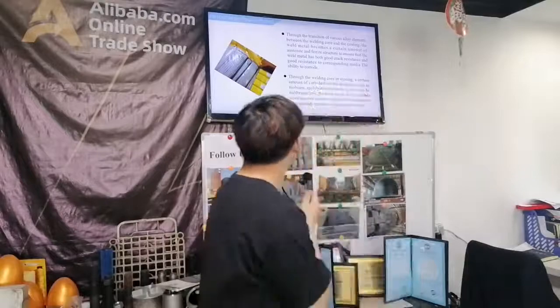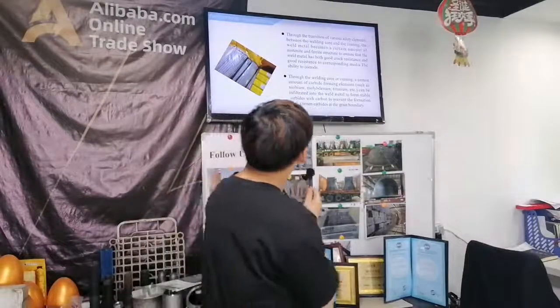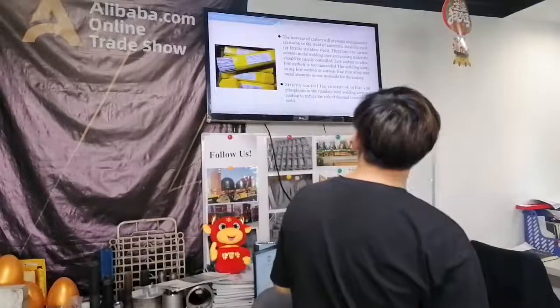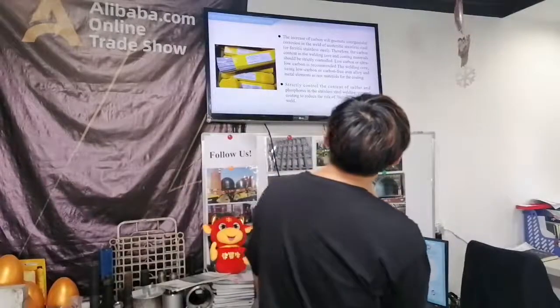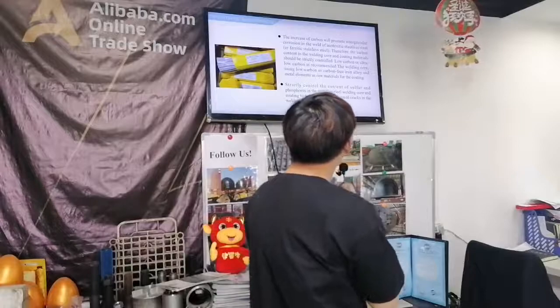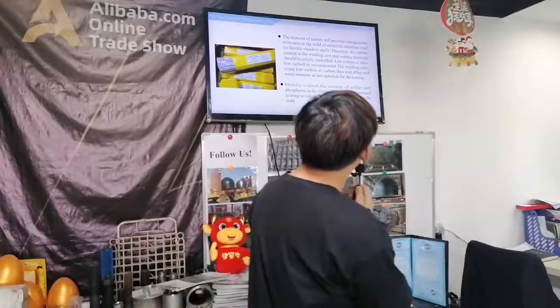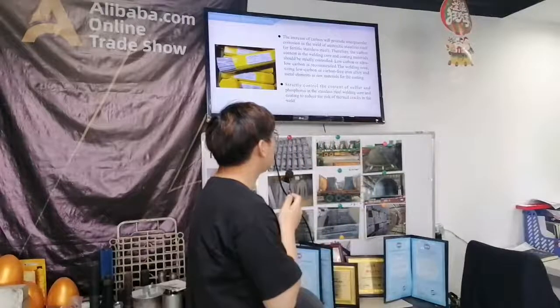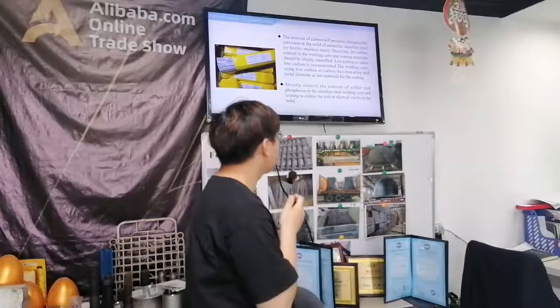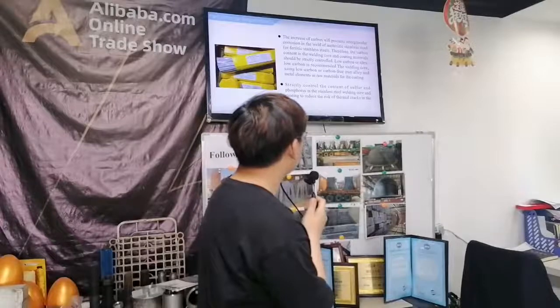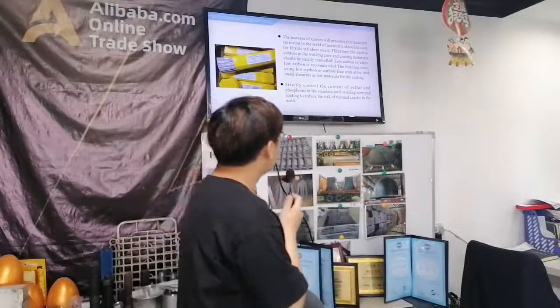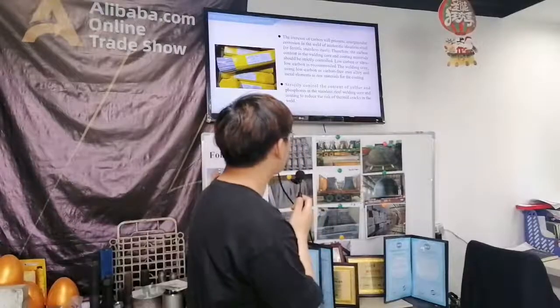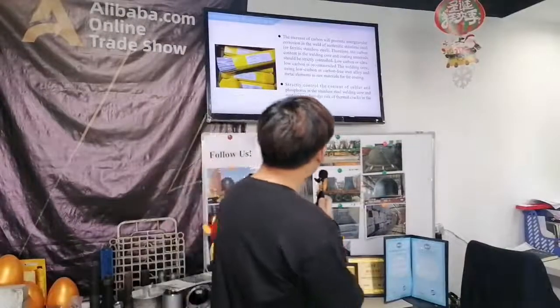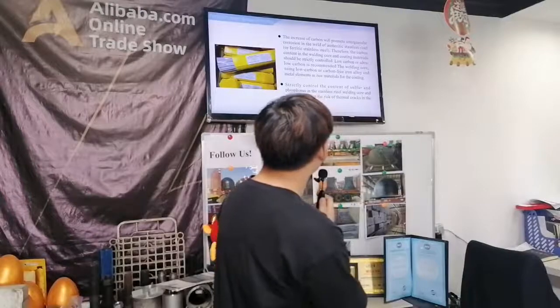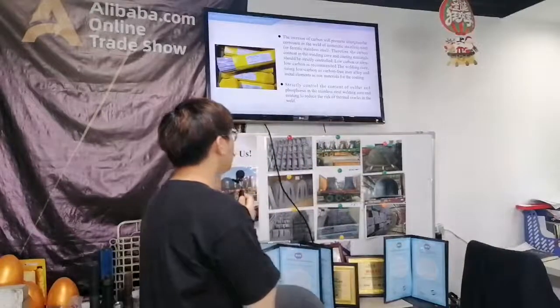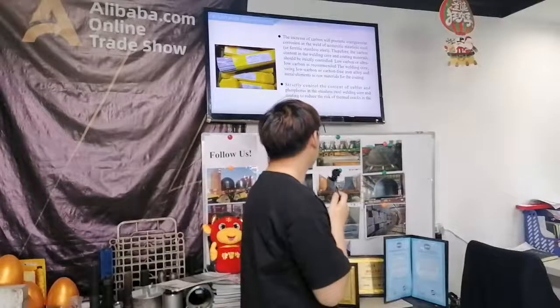And then I will introduce the performance requirements. The increase of carbon will promote intergranular corrosion in the weld of austenitic stainless steel. Therefore, the carbon content in the welding core and the coating materials should be strictly ensured. Low carbon or ultra low carbon is recommended. The welding core uses low carbon or carbon-free iron alloy and metal elements as raw material. Strictly ensure the content of sulfur and phosphorus in the stainless steel welding core and coating to reduce the risk of thermal cracks in the weld.